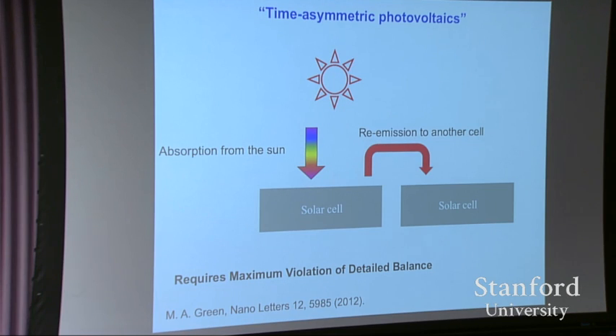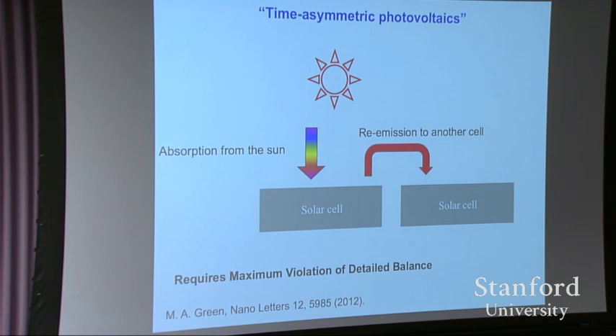Now, having pointed out the basic possibility of breaking reciprocity, if one wants to be able to implement an energy conversion scheme like this, what you would like to do is to completely reroute the emission elsewhere. So what you would need is a maximum violation of detailed balance. In other words, you would like a unity absorptivity along a particular direction and a zero emissivity back to the same direction. And that has never been done before.